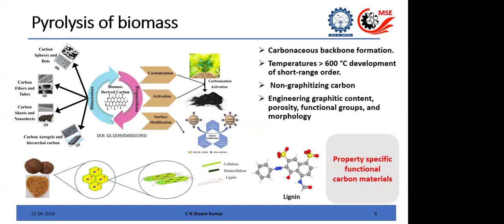So basically, when you look at it, we can think of, I would say, four things you can engineer in this. One is, as I told, the graphite content, how much sp2 or the fraction of sp2 and sp3, which again decides the final properties. Second thing, obviously the porosity, because when the volatiles and other things are removed, this carbon is inherently porous. And you can again engineer the porosity by changing the graphitization conditions